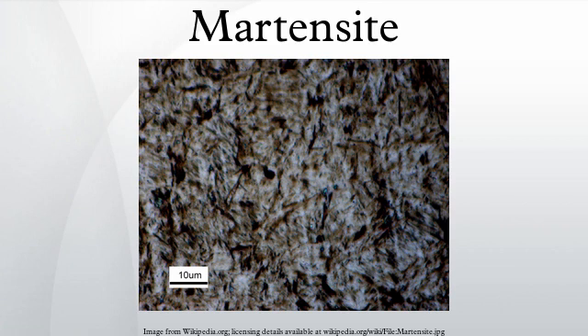The highest hardness of a pearlitic steel is 400 Brinell, whereas martensite can achieve 700 Brinell.